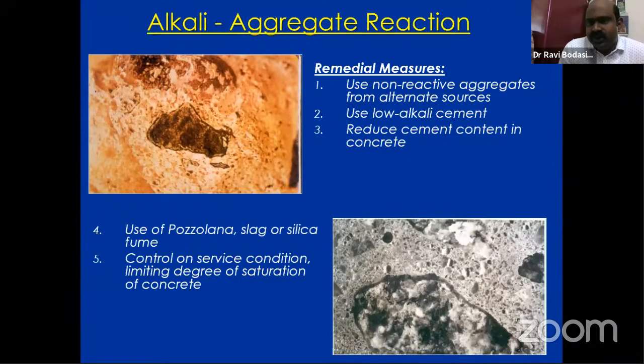The saturation condition: once the concrete is placed, immediately after 1.5 hours, when the hydration action starts, it goes from green state to plastic state and plastic state to hardened state. In this phenomenon, some silica reaction will occur. So the degree of saturation of concrete also plays a major role. This can be controlled by using proper admixtures.